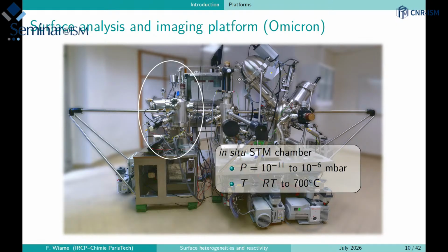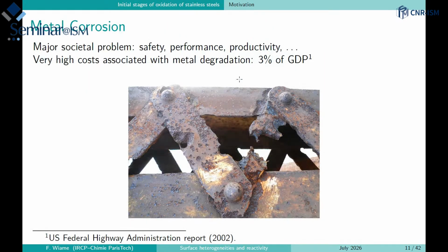Connected on the same preparation chamber, we have also an in situ STM where we can also do the exposure up to 10^-6 millibar, and we can obtain atomic resolution up to 700 degrees Celsius. So while again we are doing reaction at the surface.